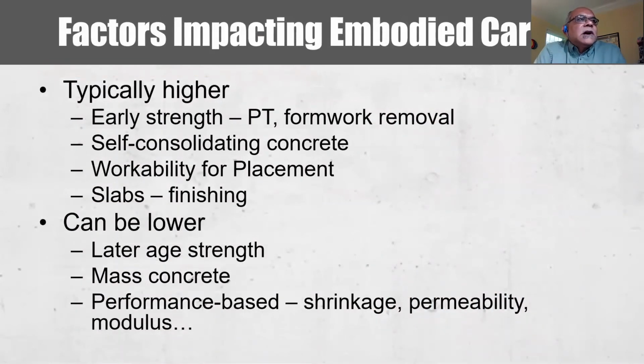Factors that impact embodied carbon: typically higher for early age strength, for self-consolidating concrete when you need workability for placements such as pumping, and if you have special requirements for finishing slabs such as hard trowel finishes, these generally increase the cement contents that are needed and therefore increase the embodied carbon content of the concrete. You can reduce that by later age strength requirements.